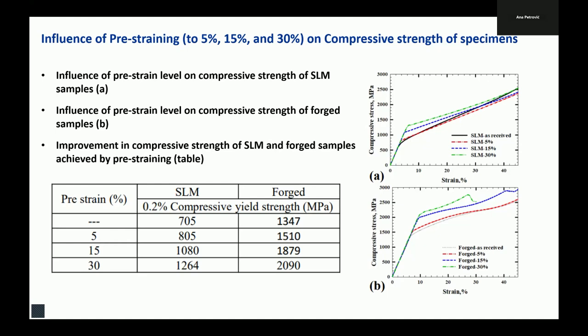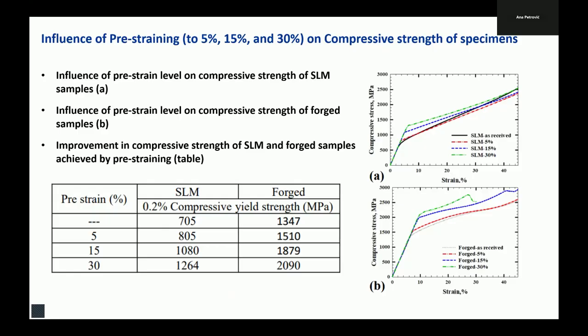In some cases, as you can see, depending on the level of pre-straining, the ductility of material is also changing to some extent. So if we try to make a quick comparison for the yield strengths of the two materials, you can see under the direction of the increase, and for the forged material, it looks like similar trends.